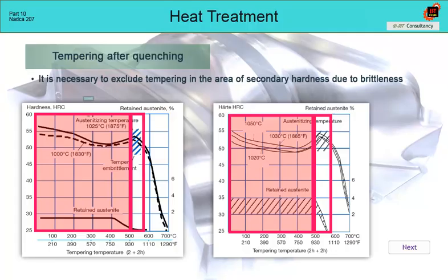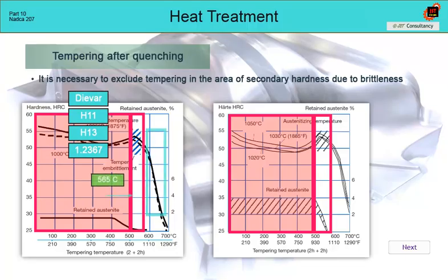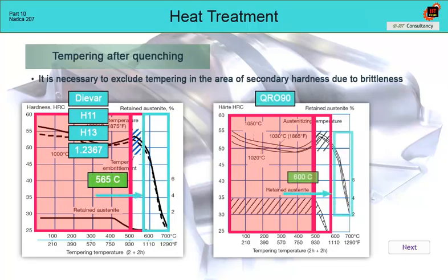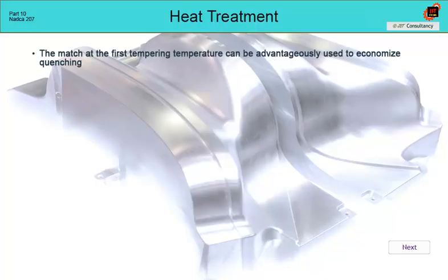For most materials, such as Dievar, H11, H13, or 1.2367, the minimum tempering temperature is 565 Celsius. Only for the QRO90 material, the first tempering must be performed at 600 Celsius. Exceptions are cases where we require the highest material hardness above 54 Rockwell, but this is not the case for die casting dies.